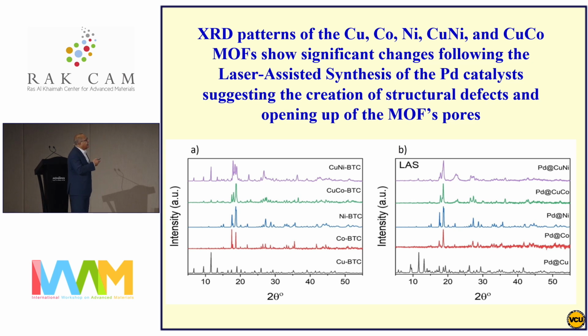So we see definite changes in the crystal structures of the MOFs, which suggests opening of the MOF pores or creating structural defects through the laser irradiation of the MOFs in the presence of the palladium ions, which reduces the palladium ions.